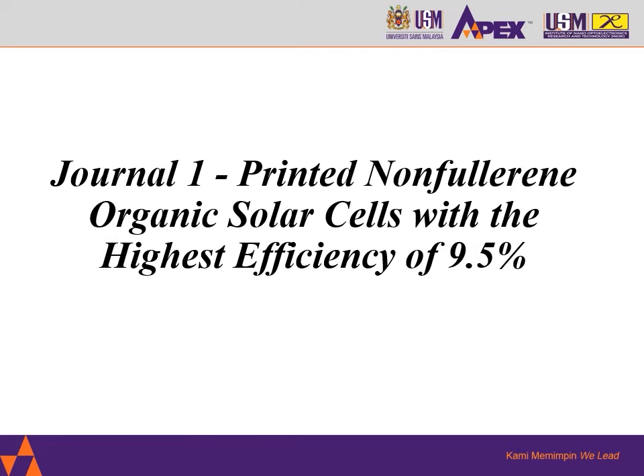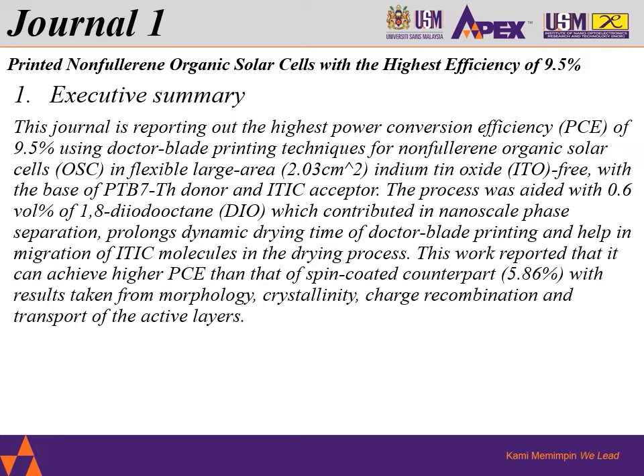So let's go to the first journal over here, which is the printed non-fullerene organic solar cells with the highest efficiency of 9.5%. This first journal is actually reporting on the highest power conversion efficiency, which is PCE, of 9.5% ever reported using doctor-blade printing techniques for non-fullerene organic solar cells, or OSC in short, in a flexible large area, which is 2.03 centimeters squared, on ITO-free, with the base of PTB7-Th donor and ITIC acceptor.